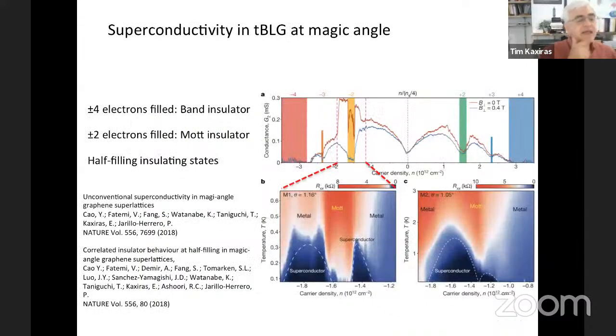Okay, now the big surprise came with this set of experiments in 2018 by Pablo Jarillo-Herrero's group. And what you see here again is the horizontal axis is doping. So you can think of this as moving the Fermi level on the energy axis. And the vertical axis is the conductance, which is again a measure of the density of states. And again, you see these densities of states that I was mentioning earlier, separated by large gaps from other states, but you also see mini gaps. So there's a mini gap here and another mini gap here.